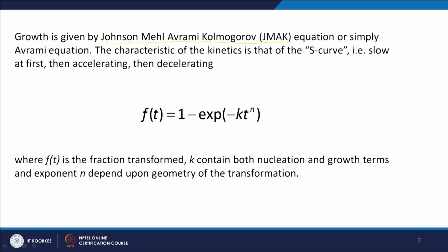Or simply we call it the Avrami equation. The characteristic of this is that it gives you a typical S curve, which shows that the growth kinetics are slow initially at first, and then it accelerates, and then at the end it decelerates. This is the typical growth kinetics you will find in a large number of systems. For example, if you want to see bacterial growth, then also you will have a similar S curve. So, it is a very common characteristic, and it is given by an Avrami equation.